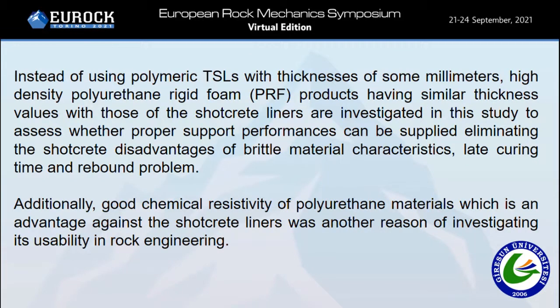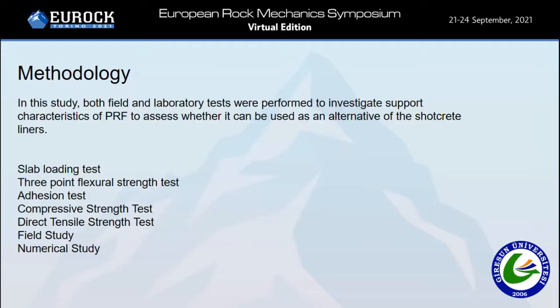Instead of using polymeric TSLs with thicknesses of some millimeters, high-density polyurethane rigid foam products having similar thickness values with those of the shotcrete liners are investigated in this study to assess whether proper support performances can be supplied by eliminating the shotcrete disadvantages of brittle material characteristics, late curing time, and rebound problem. Additionally, good chemical resistivity of polyurethane materials, which is an advantage against the shotcrete liners, was another reason for investigating its usability in rock engineering.